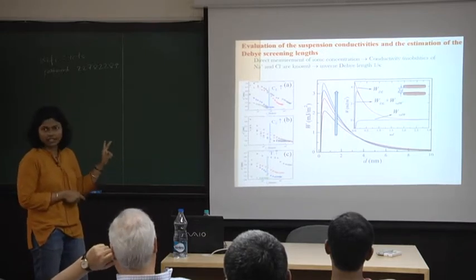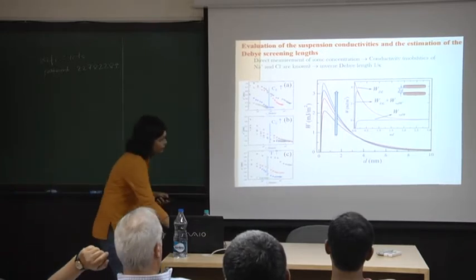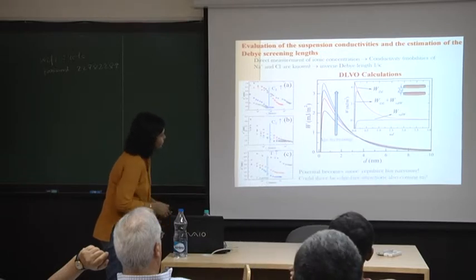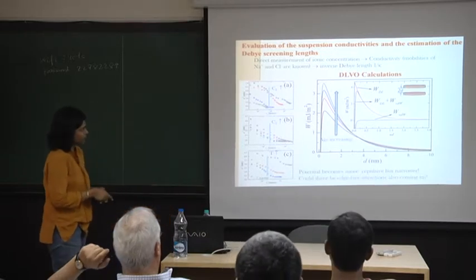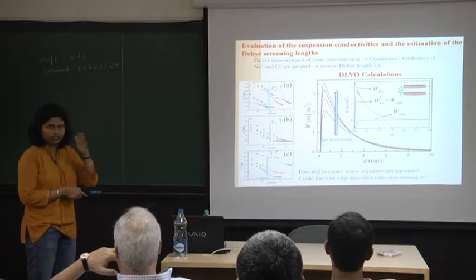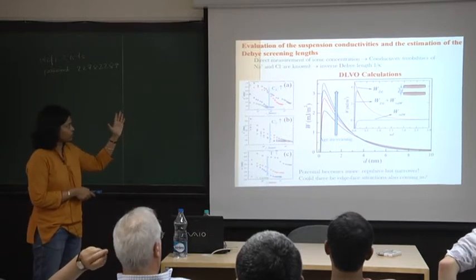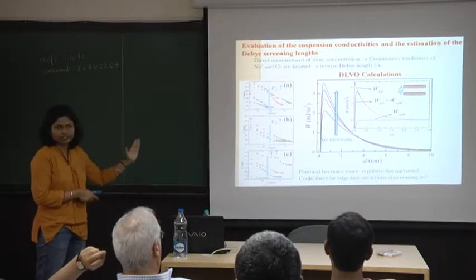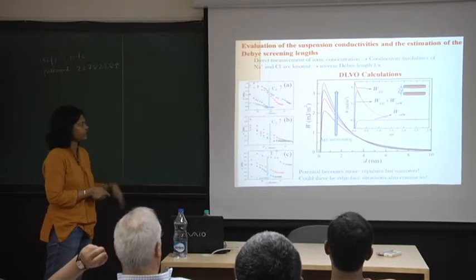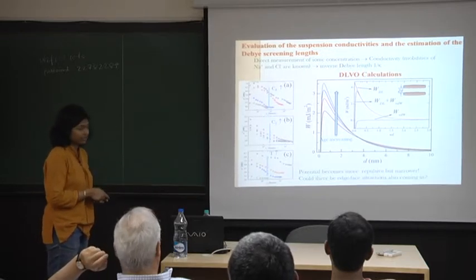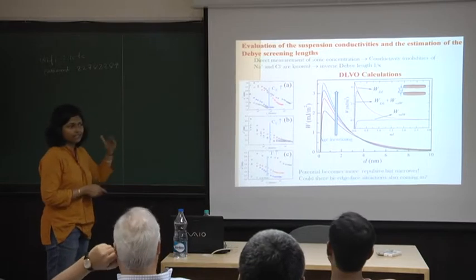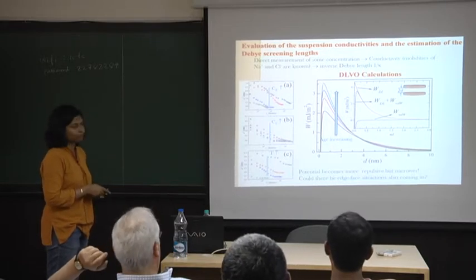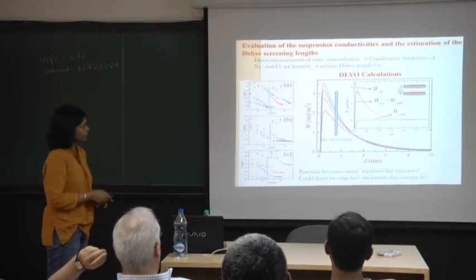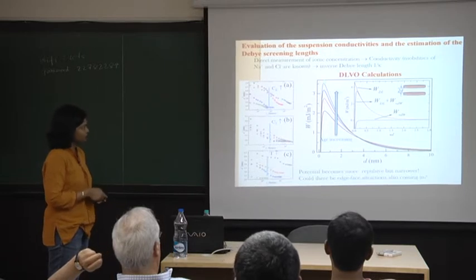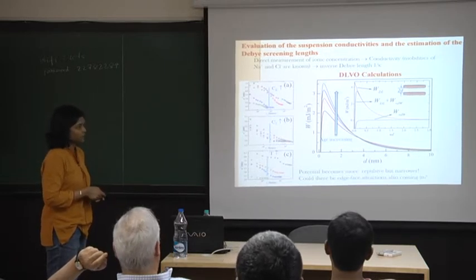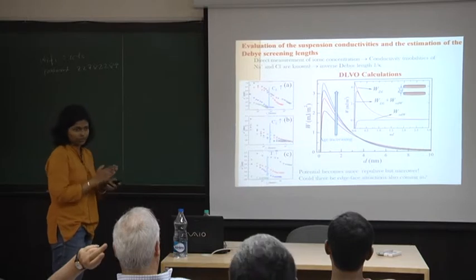Just two things I'd like you to notice here. This is when age increases. The arrow going up is the age of a particular sample; these are samples at a fixed salt concentration and fixed temperature, but the age is increasing. You see two things: as the age increases, the repulsive peak becomes stronger, but the breadth becomes narrower.